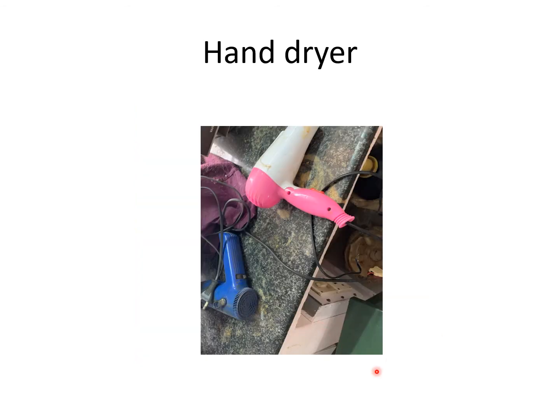And after preparing the samples, we know that steel samples require 4% nital. So we have to etch the sample using nital, and then we have to use a dryer to dry the sample. Then only the dry surface will be